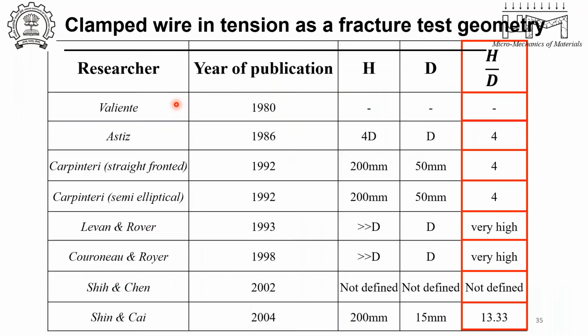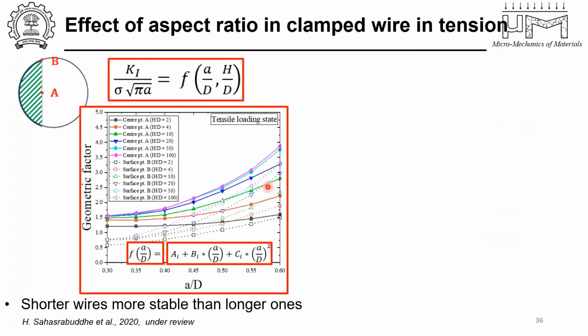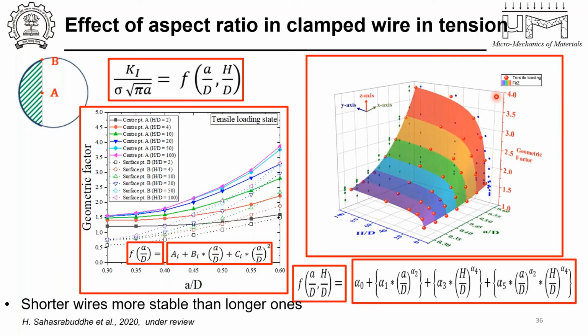So that is what we wanted to recalculate by doing these geometric factor calculations for different H/D ratios. This is what one of my students did, using which you can see that for small H/D ratios, the geometric factor is still a monotonic increase, but it stabilizes and then grows very gradually at longer A/W ratios, or A/D ratios in this case. Whereas for longer wires, the increase is much sharper. So one can, of course, fit it into equations, and we could also fit it into a three-dimensional equation where you add the H/D along one axis and the A/D along the other axis, and provide solutions as a combination of the two factors. Again, the conclusion remains that shorter wires are more stable than longer ones.